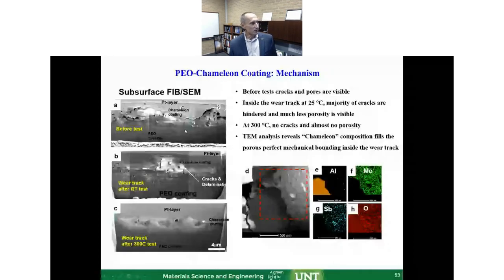And interestingly, what we've noticed is this: when the coating is made, and this is before running the test, this is the PEO coating here, the chameleon on the top, and this is a platinum layer just to make the TEM sample. You can see here the defects and cracks inside of the chameleon coating. Okay, we have open porosity in PEO, and we certainly can expect some open pores not yet filled with chameleon. That's what we can see here.